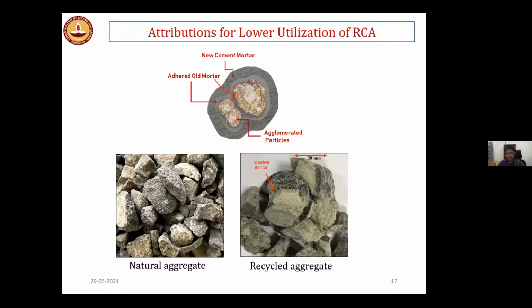So you can see the natural aggregate will be like that. But in case of the recycled concrete aggregate, it will have the natural aggregate, definitely, but it will also have adhered mortar content, right? Or you can see some two aggregates sticking with each other. We call them the agglomerated particles, right? So this is the main reason, the adhered mortar content, mortar from the previous building.